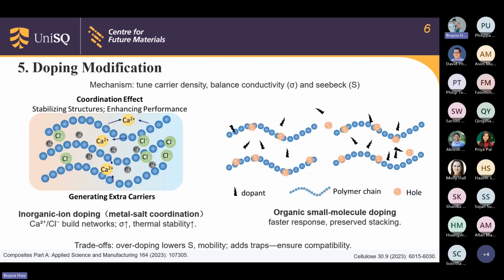And the third mechanism is doping modification. Doping is not just about adding as many carriers as possible. We set the carrier type and the amount so that conductivity stays high, but the Seebeck coefficient does not collapse. One approach is inorganic ion doping. This line of work adds metal ions, for example, calcium with chloride, to the polymer network. The ions coordinate with the chains and act like tiny crosslinks, which creates extra charge carriers and raises electrical conductivity while keeping the film more stable at high temperature.